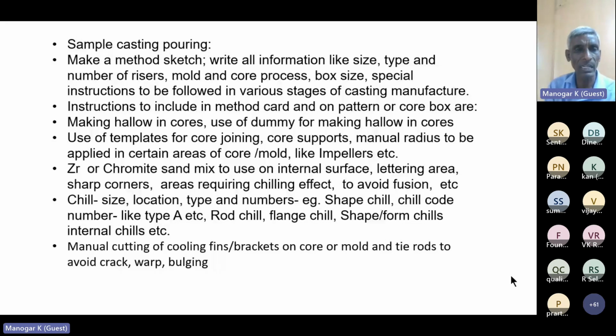So especially this is important in steel castings to avoid any crack. And marking, cutting in the mold brackets, cooling brackets to avoid cracks. Use of templates for core joining, core pasting, since two halves are always joined in steel foundries. So you make gauges for that. And in some areas we use zircon or chromite sand to avoid fusion, and in between seals to avoid cracks and avoid fusion. We will put it in the fillet areas.